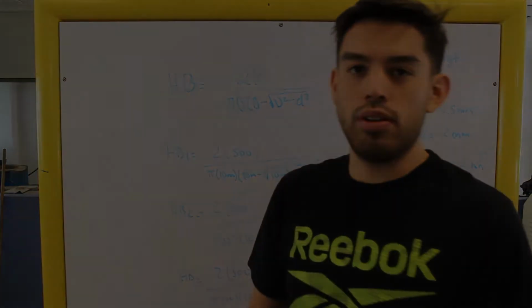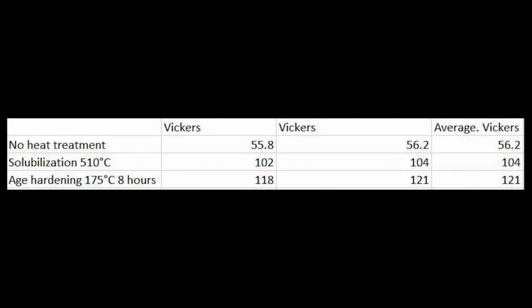And in the last one, in the age hardening process at 8 hours, we got 121 hardness. When we did our bigger test, we see that the no heat treatment piece shows lower hardness than the others, the solubilization and the age hardening at 175 for 8 hours. So with this process we know that age hardening is really useful to increase the properties of our materials, to increase the hardness more than in the others. Also, it's very important to take care of the time and the temperature of our process because otherwise it will be counterproductive to our piece of metal.